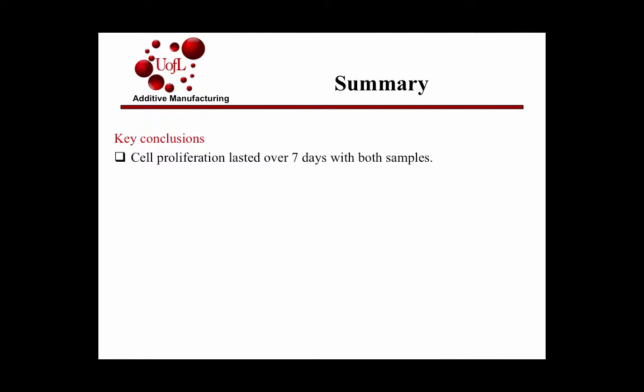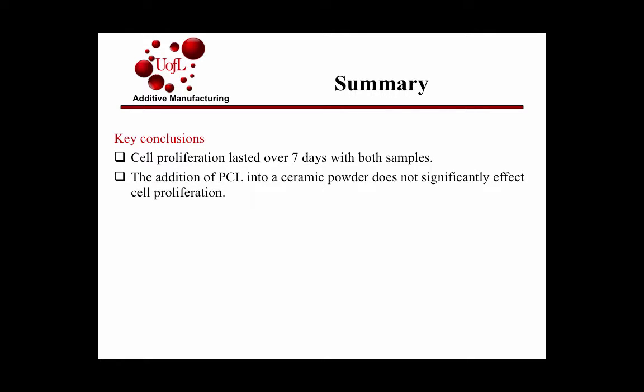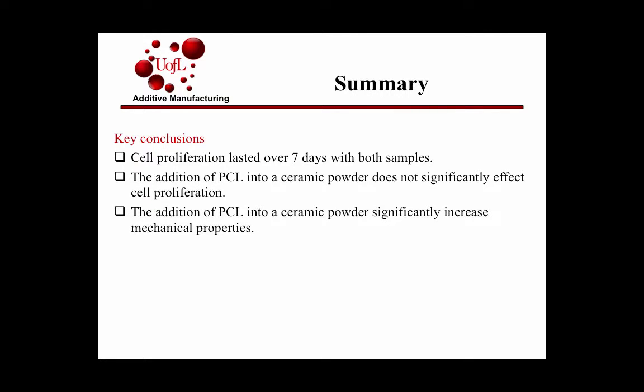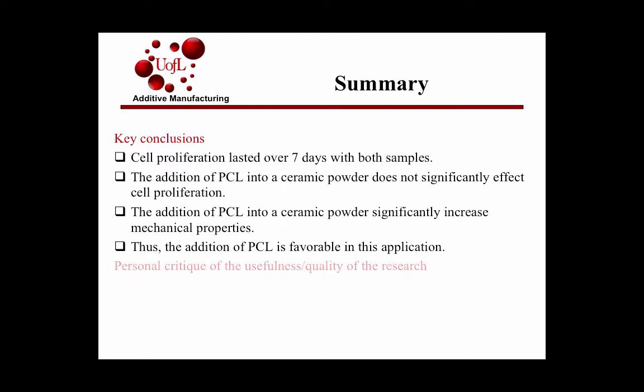So cell proliferation lasted over 7 days, which they thought was good, is what you want when you're putting it into somebody. The addition of PCL does not significantly affect cell proliferation, even though it kind of looks like it does with the chart. Like I said, it didn't really matter. The addition of PCL significantly increases your mechanical properties. And so they concluded at the end that the addition of PCL is very beneficial when adding it to the ceramic powder.